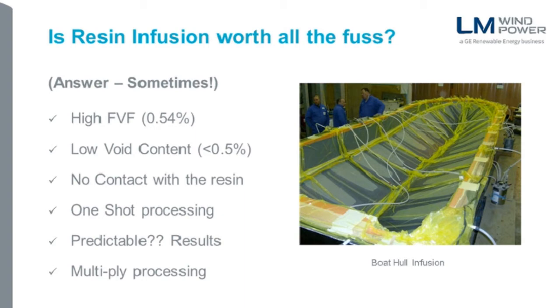You need to be very sure of your infusion strategy. Have you set the consumables up in a way that means everything gets wet out, everything gets saturated with the resin? Have you got a process where you won't spring a leak or pull a pipe out halfway through the process? Because when it's dry, the pipe is light because it's not got resin in it, if that's a resin inlet pipe or a vacuum pipe. But as soon as you've started the infusion, it gets filled with resin, it's heavier, and it disconnects itself from the bag, and all of a sudden you've got a leak.